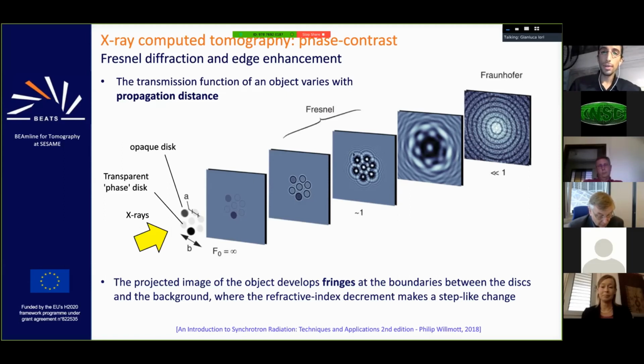In between, there is an area of near field diffraction, where you can see Fresnel diffraction, where you can see fringes arising at the edges of the sample. So the transmission function of an object varies with propagation distance, and the projected image of the object develops fringes at the boundaries between disks and background. So phase contrast tomography can actually exploit these features to reconstruct and extract information on materials like these transparent disks